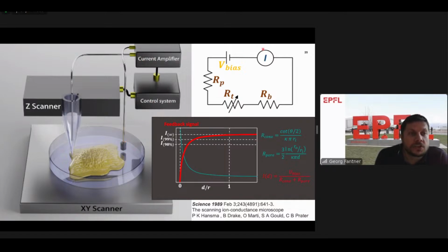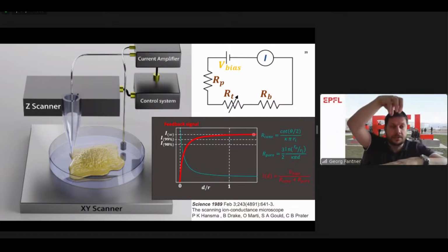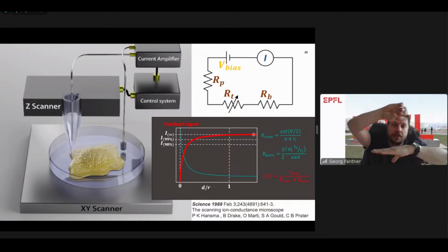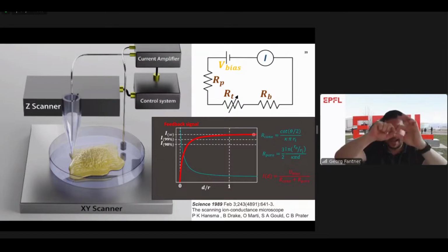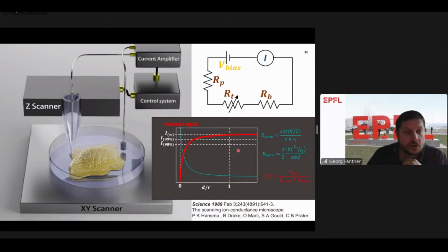When we apply a voltage, we create a closed circuit, voltage source, and we have a couple of resistances in this circuit that determine the current. Now, if we are far away from the surface, the current is high. But the closer we get to the surface, if you think of this as a little hole that ions can flow out of, when we get closer and closer to the surface, the gap between this hole and the surface gets smaller. And so it reduces the area that the ions can flow through, and the current will drop. And this is what we measure. The closer we get to the surface, the more the current drops.